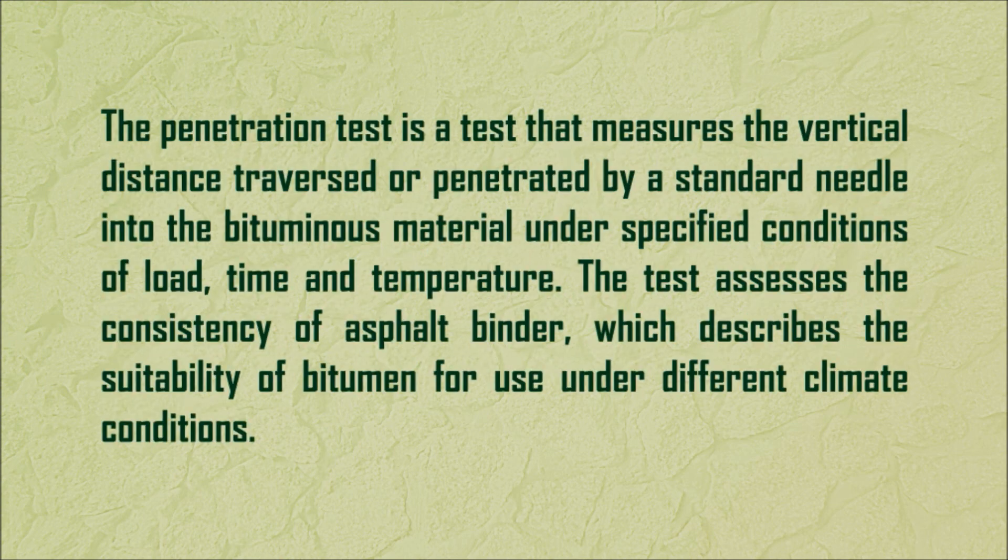The penetration test is a test that measures the vertical distance traversed or penetrated by a standard needle into the bituminous material, under specified conditions of load, time, and temperature. The test assesses the consistency of asphalt binder, which describes the suitability of bitumen for use under different climate conditions.